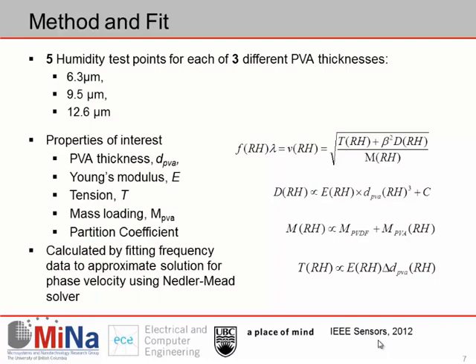We then looked to measure the properties of PVA thickness, which can be found in the stiffness, the relation for stiffness, Young's modulus, tension, mass loading, and partition coefficient, which is the ratio between the amount of solvent in the polymer and the amount of solvent in the ambient area.